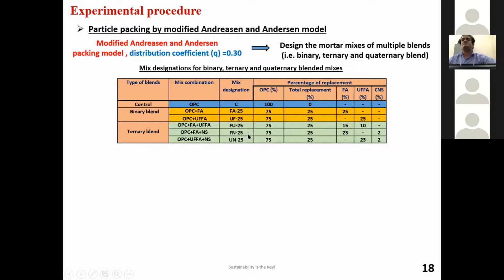Now, when I gave this combination, the best fit curve gave me the best particle packing density: 75 OPC, 15 fly ash, and 10 ultrafine fly ash. Then 75 OPC, 23% fly ash and 2% nanosilica. Same thing, 75% OPC, 23% ultrafine fly ash and 2% nanosilica. So I am restricting my nanoparticles to only 2%. Only 2%.